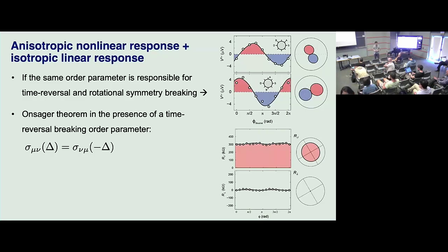I have a question about the experiment. How easy is it to fabricate a sample that can have such homogeneity? Do you have any experimental way to improve that? Right, so there's a reason that I'm showing most of the measurement on Bernal bilayer. The homogeneity is fairly low. So far, all the Bernal bilayer that we looked at, 4 or 5 different devices, essentially all have the same response. For graphene moiré, twisted trilayer, twisted bilayer, the success rate is lower.